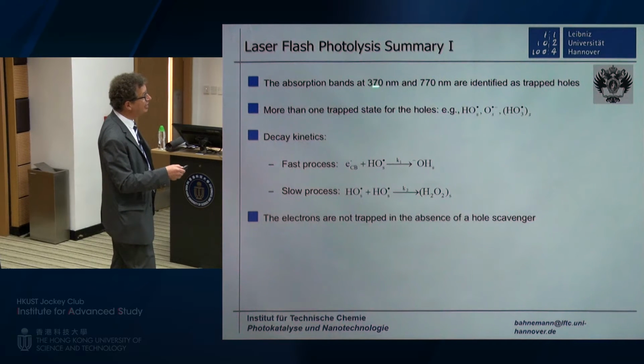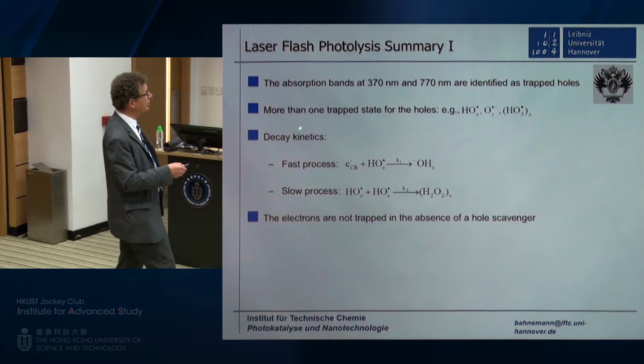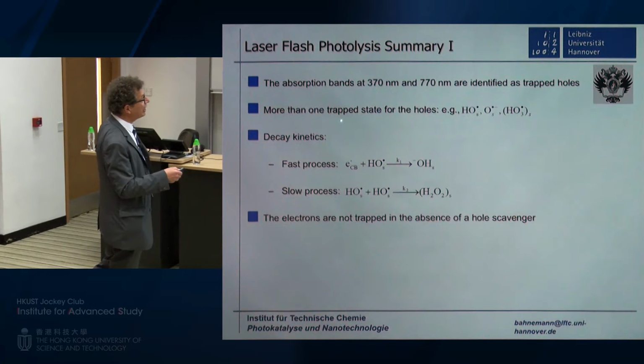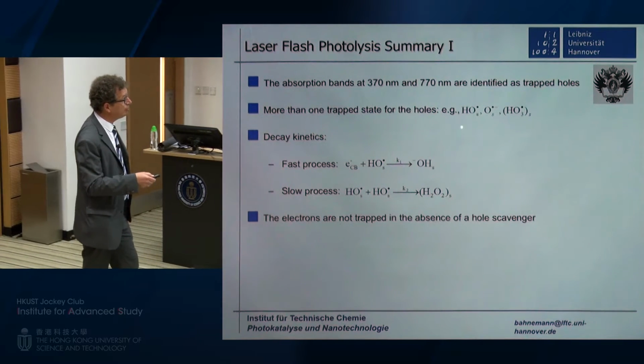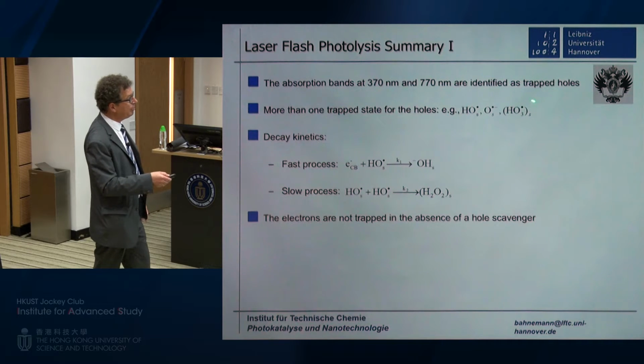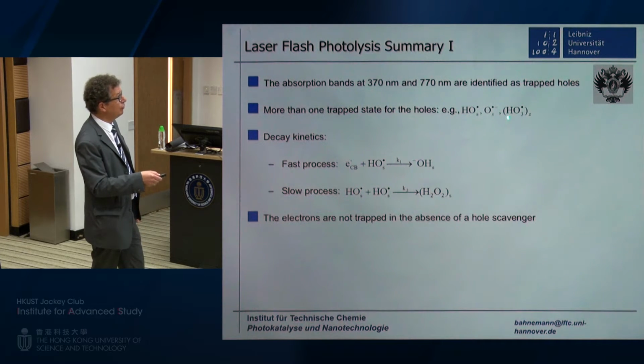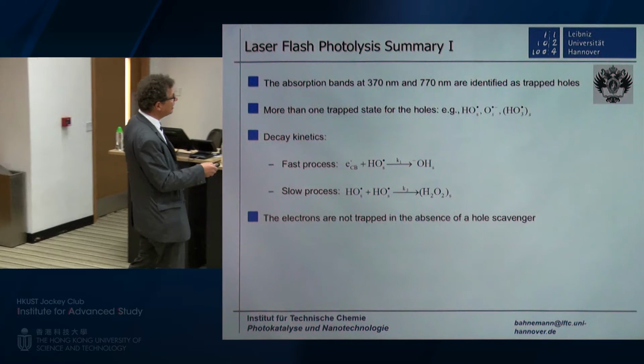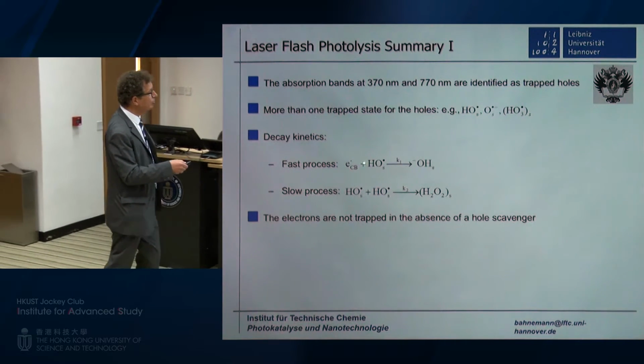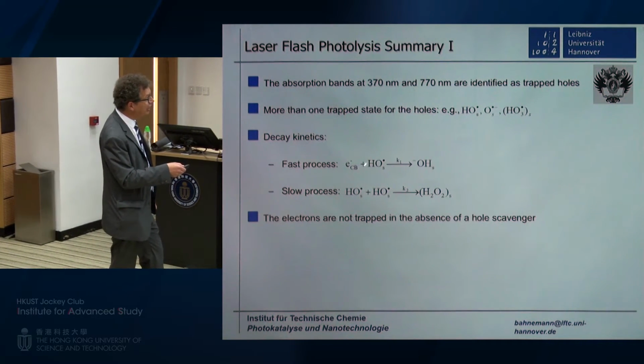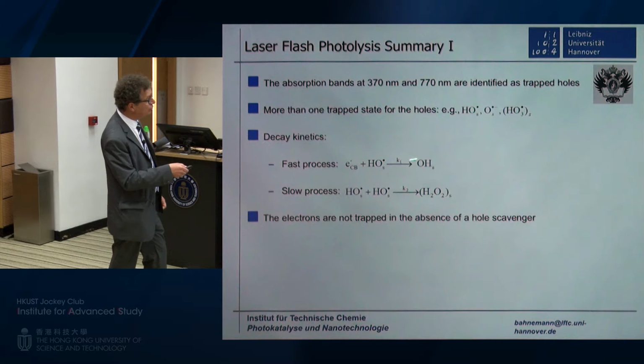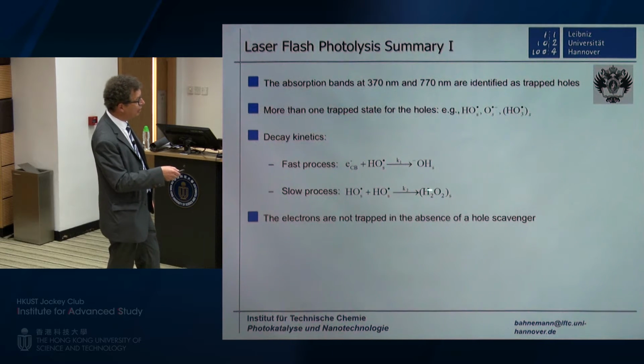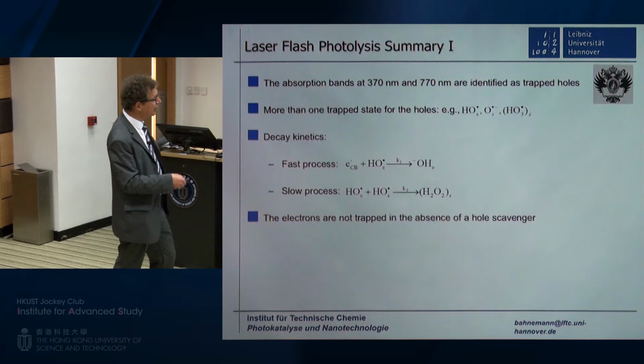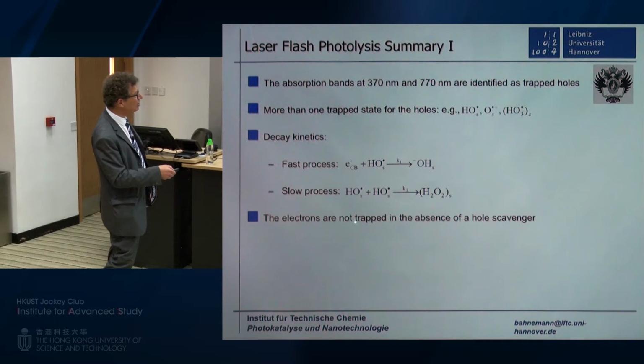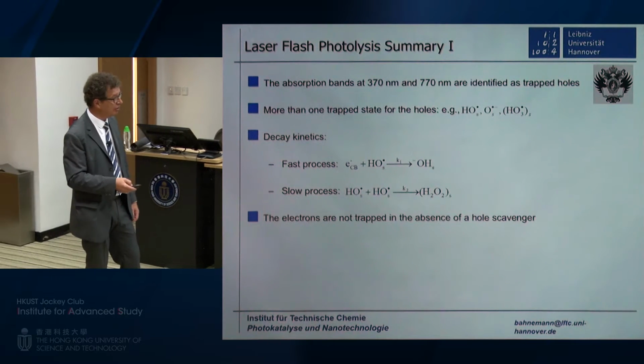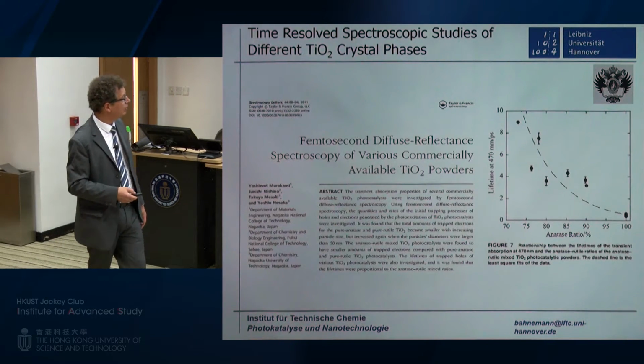We identified these transients as the trapped holes. The kinetics tell us there is more than one trapped state for the holes. So maybe you might also invoke something like an ozonide on the surface. And the decay process seems to be that the first decay is the untrapped electrons with the trapped holes, and the slow process is then the recombination of the charge carriers. Electrons are not trapped in the absence of hole scavenger, something we still don't understand why.